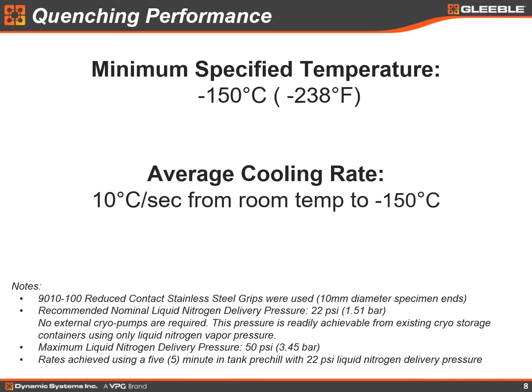I will point out that the average cooling rate is not that fast. We do get a lot of customers that have questions about cooling with liquid nitrogen, and they're looking for liquid nitrogen not for cryogenic temperatures but for faster cooling rates. And unfortunately, liquid nitrogen does not really give a faster cooling rate than water. This is due to a couple of reasons, primarily the Leidenfrost effect, or the barrier layer that occurs when you try to quench a sample with liquid nitrogen, and also the fact that liquid nitrogen has a much lower heat of vaporization than water does.